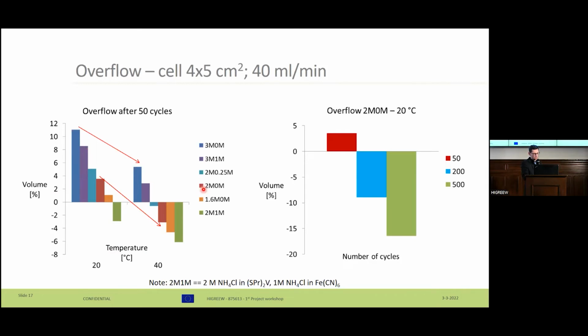And we also try to find best conditions. So maybe if we cycle only 50 cycles, battery with 2-0 combination at temperature 20 degrees, maybe we will get overflow equal to 0, but there is another problem. If we do more than 50 cycles, overflow turns to the other side. I think it is caused by the membrane, and if we want to get better values, we should focus on the membrane and get better balance between the half cells.